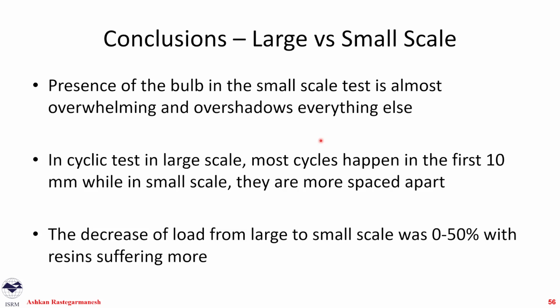For large and smaller scale tests, the presence of the bulb in a smaller scale test basically overshadows everything. So if you have a bulb in a small scale test, it basically scrapes everything off. And most of the cycles in a smaller scale test happen in the first 10 millimeter in larger scale tests, but in smaller scale tests, they are spaced apart. And the decrease of the load from large to a smaller scale test can be anything between 0 to 50%. It's not as simple as saying that half of the embedment means half of the load.